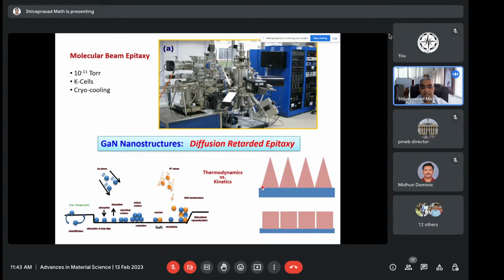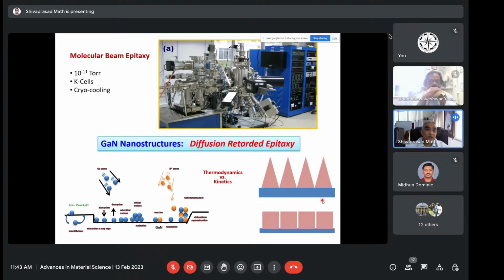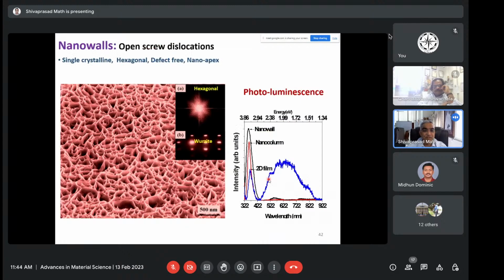So we thought this could be sorted out if we could make nanomaterials of these wedge shaped structures. We were struggling to find how to make these wedge shaped structures by growth kinetics, not by lithography or anything, because lithography can create other problems, and we may not be able to reach the dimensions we are talking about. So how to create these structures using just the kinetics of growth is something we kept on trying. With a lot of hard work, we were able to come to a structure like this. It was very interesting. You can see this looks like a very bad porous material, but it has been amazing.